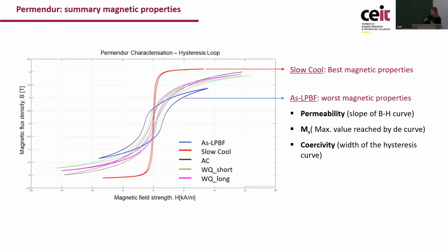So relating this microstructure with the magnetic properties, again, what we see is, as Jose Manuel said, the good soft magnetic properties are the ones in red. So they have very low coercivity, but high permeability and high magnetization saturation. And these were related with the ones slow cooled. So heat treated and then slow cooled. And the worst soft magnetic properties were for the AM microstructure, and in the middle, as we say, the ones that have been heat treated with different cooling rates.